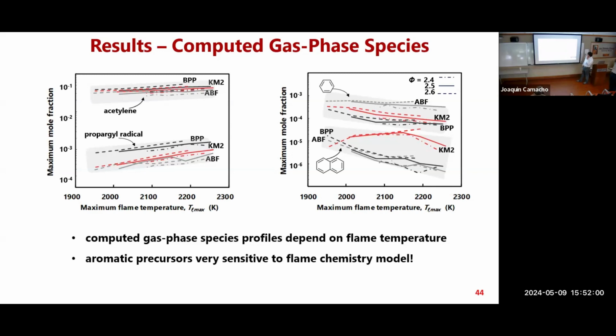Yeah, it's taking some time because I know how important it is to be confident and put a good error bar around this based on sound reasoning. But this is orders of magnitude different here. And in this area of research for soot formation, both the soot concentration and the precursor concentrations, they're happy with a factor of 2, like plus or minus 100%. That's a reasonable agreement in this area.